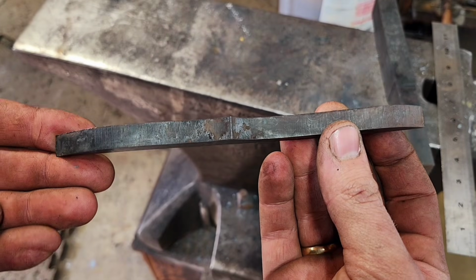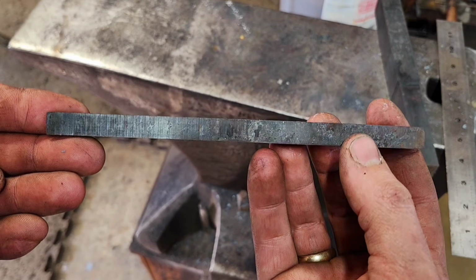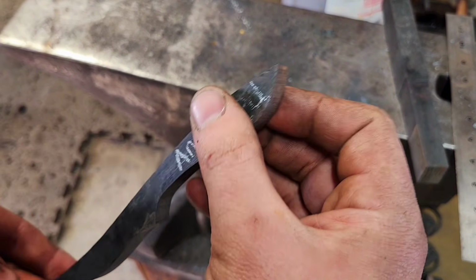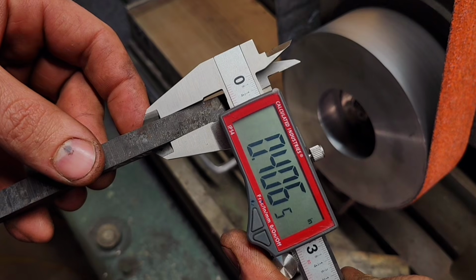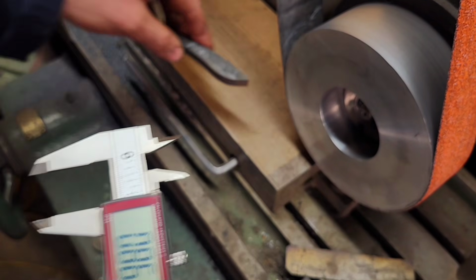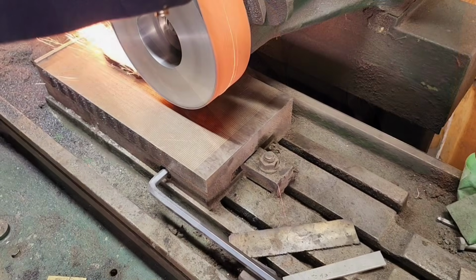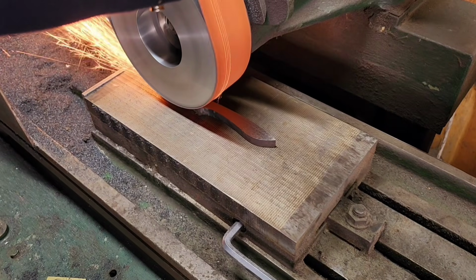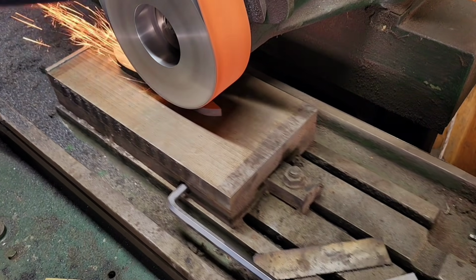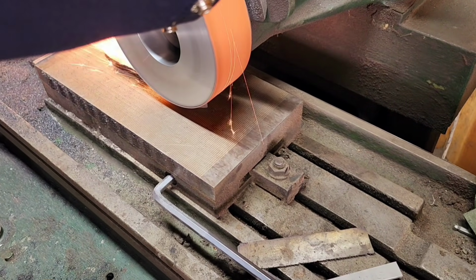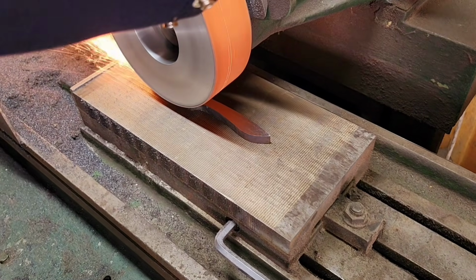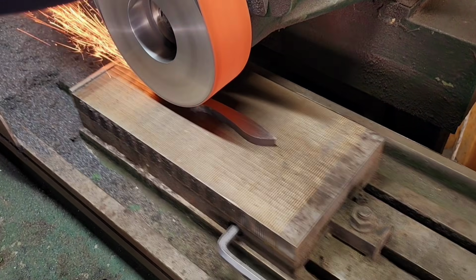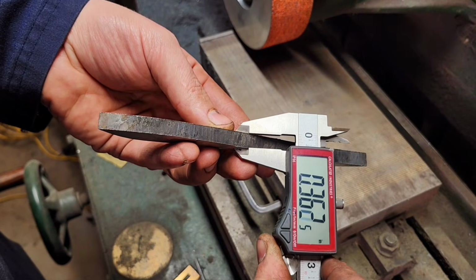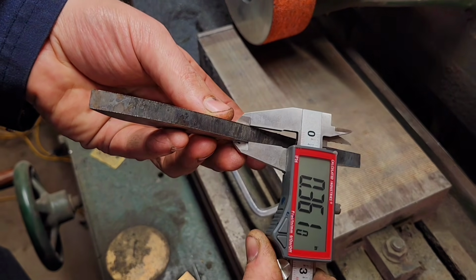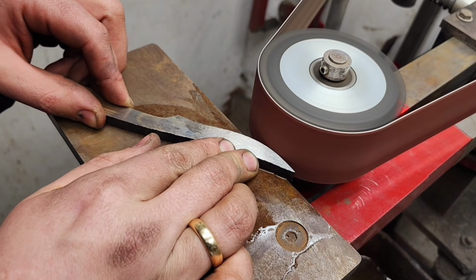So into some heat treating cycles. And here's the knife fully annealed. We're at 406 thousandths of an inch here, so we're going to take that down a little ways. The surface grinder with the belts really does it quite efficiently and quickly. Just a hair over 360 thousandths. Perfect.